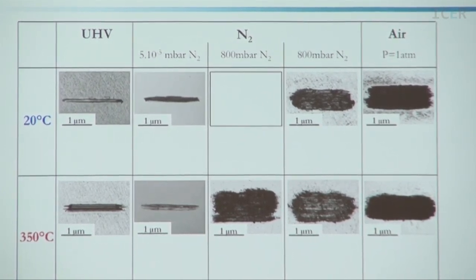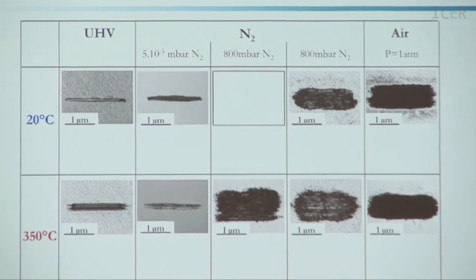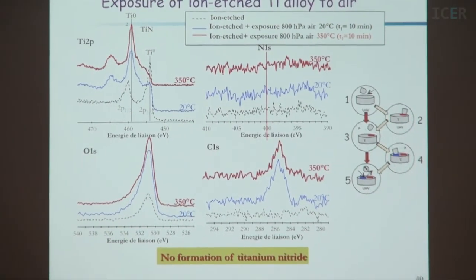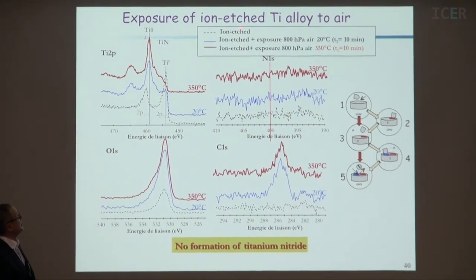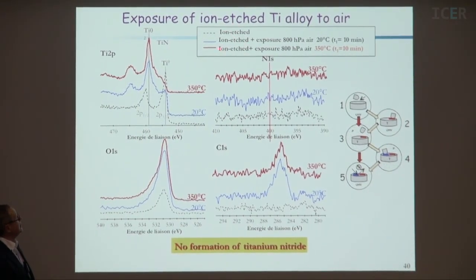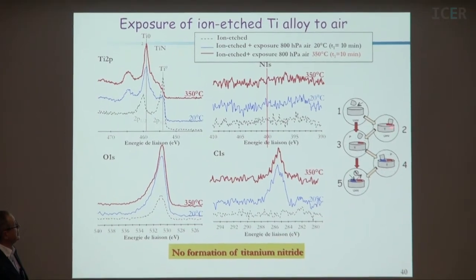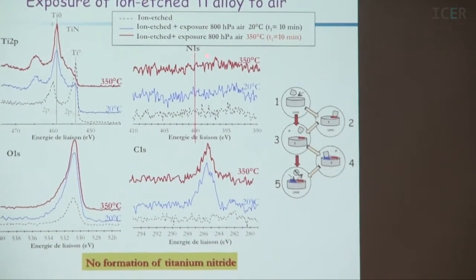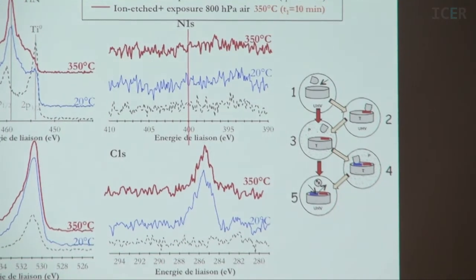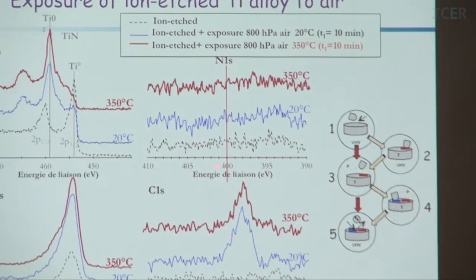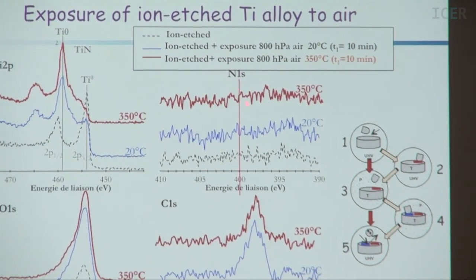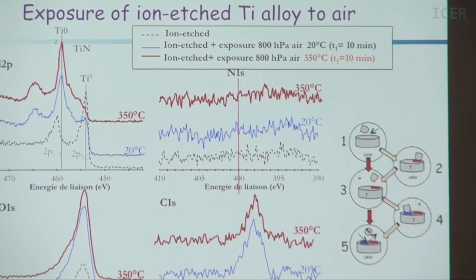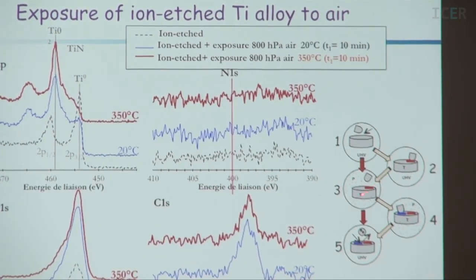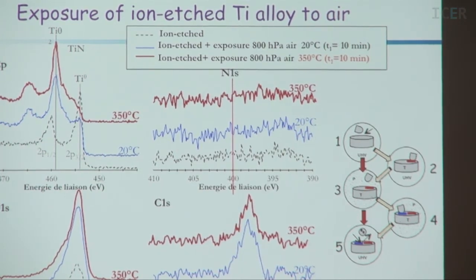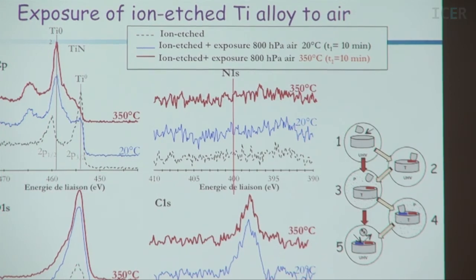So wear is drastically enhanced by the presence of oxygen and nitrogen. And now if we look at the surface, typically this is an ion-etched surface, this one here, after being exposed to the gas. As you can see, it's maybe complicated, but if you look here, there is no nitrogen on the surface. So the gas here does not react with the tribostressed surface, contrary to the case I showed you before with sulfide, phosphide, and so on.